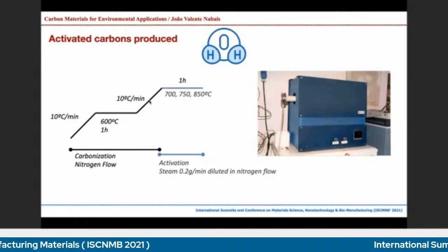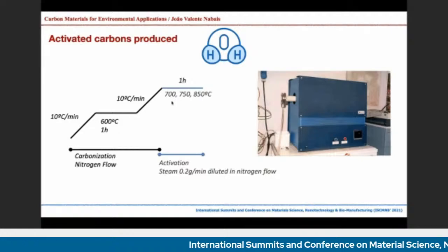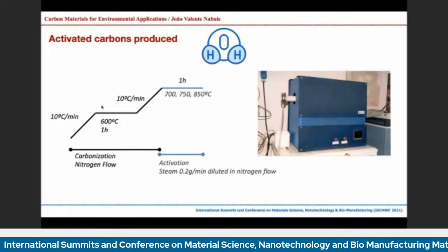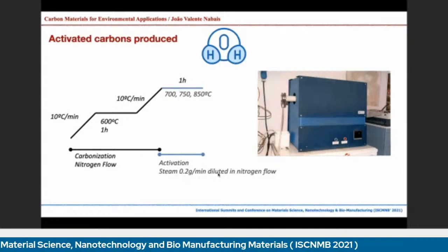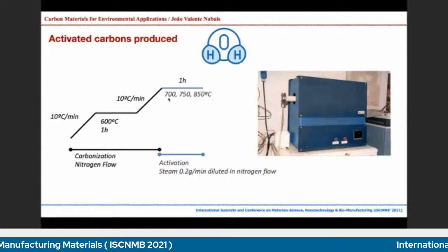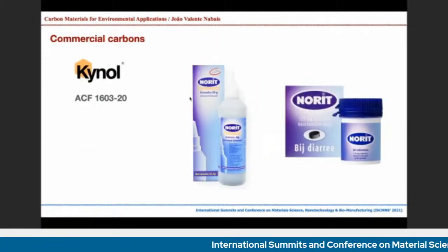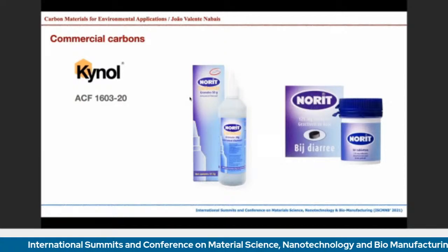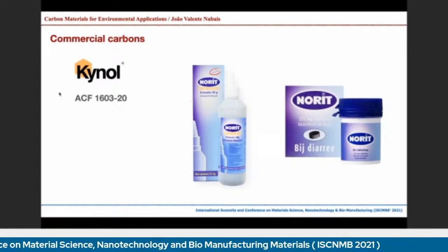The process is a little bit different. It's a heating process as well, with a pyrolysis. For the carbonization we have used a slightly higher temperature, but then we have done the activation with steam, diluted in nitrogen flow, for 1 hour at these 3 different temperatures. Besides the laboratory-made carbons, we have used 3 commercial carbons just to compare with the work that we are doing.